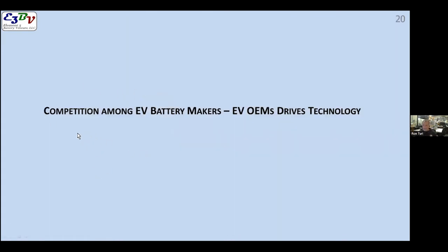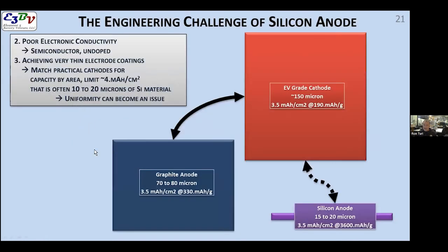So what else are they doing here? They're also looking at anode materials. Anodes take up a lot of space. Graphite is not that dense. It's got a density of about 2.2 grams per cubic centimeter, and it's fluffy because there's a lot of space in between the graphite particles. And as a result, you have like 70 to 80 microns of graphite in an anode.